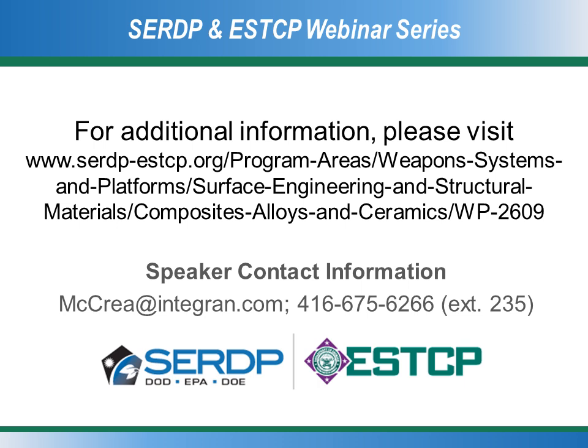And as I said, with our process here, we've never had an occasion where we've had to replace the solution. Sometimes you see some different contaminants come in from the substrates that you're plating. Some of the metals might dissolve a little bit, but they all are managed to come out of solution and they don't cause problems. So from that perspective, it's very robust. There's not a lot of additives, not a lot of components that break down. So it's quite usable and quite reliable from a long-term perspective.